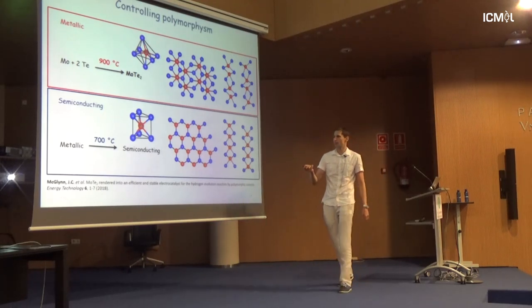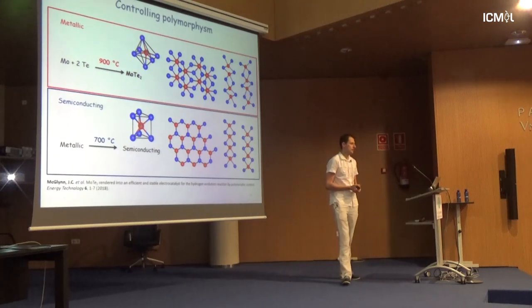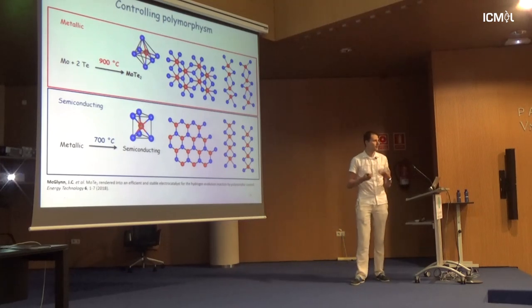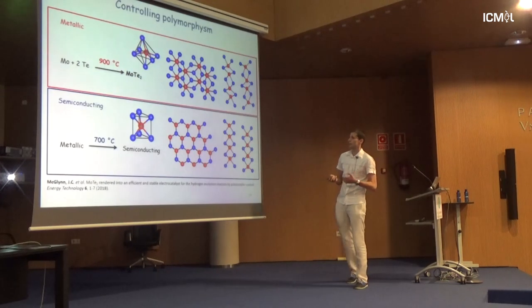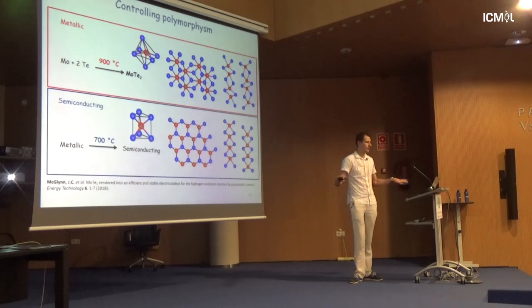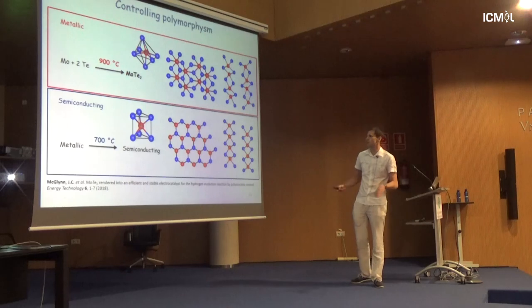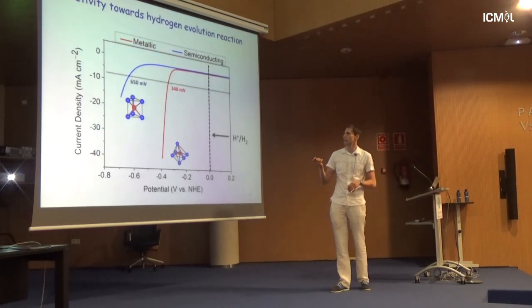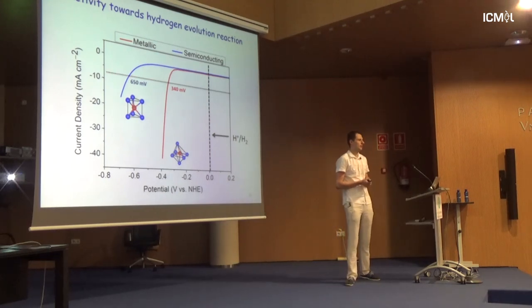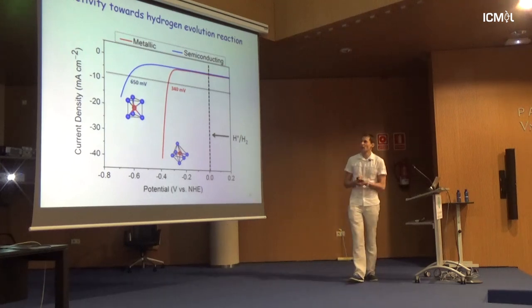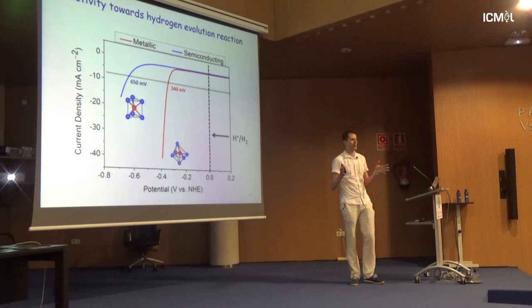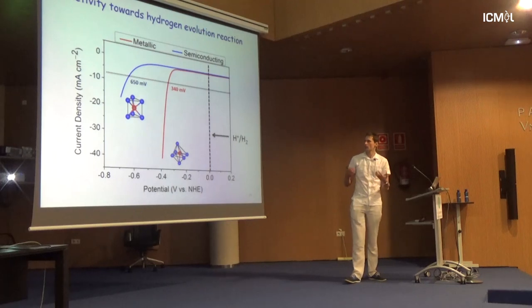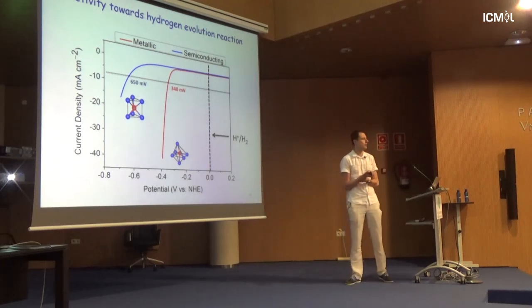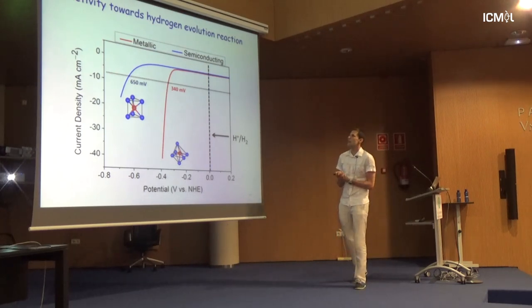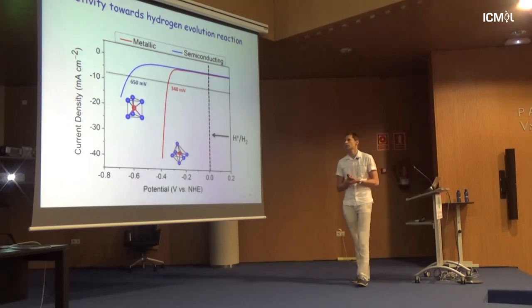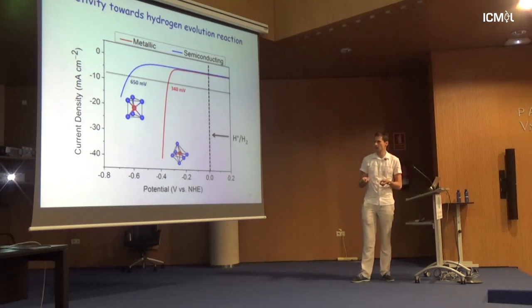And then what you can do is simply take this metallic phase and heat it to 700 degrees, and it turns into a semiconductor. So you can do an isomorphic transformation. And this is what we did. We isomorphically converted, and the structure was absolutely identical. Microstructure was absolutely identical. And what we really see is a huge difference between metal and semiconductor. For me, it was very, very important to prove that by playing with crystal structure and with the properties of a material, you can really show a genuine change in electrocatalytic performance. So in a sense, we confirmed that the metallic phase is genuinely a better catalyst.